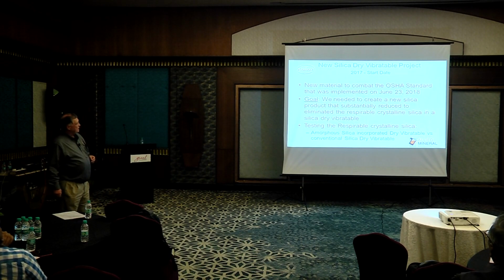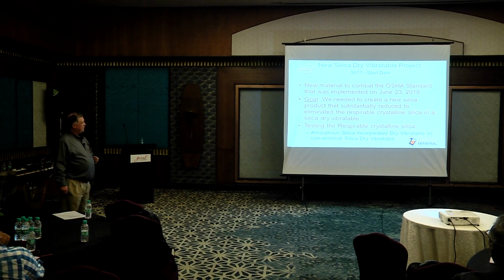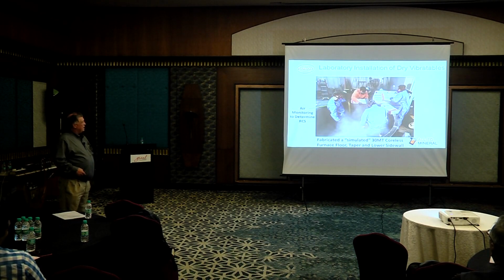dry vibratables. Testing was done on amorphous silica incorporated in dry vibratables versus conventional silica in dry vibes. So again, here it is. You can see that all these workers are hooked up with monitors so that we can track exactly how much exposure they have to that particular grain size.